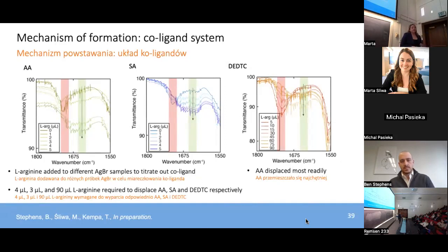So we see through these experiments that it only takes roughly 4 microliters and 3 microliters of L-arginine to be introduced into the solution to effectively displace the ascorbic acid and salicylic acid, respectively. And this confirms the likelihood that in our synthesis, where we introduce a lot more than 4 microliters of L-arginine, that process is exactly happening, where the L-arginine is kicking out the ascorbic acid, and in that way acting as a functionalizing ligand to drive that silver-silver bromide dimer growth.